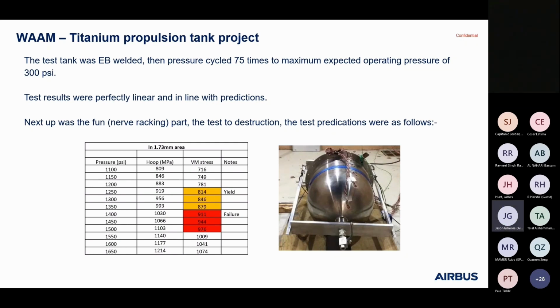So these are the test predictions. We predicted that it would yield between 1250 and 1350. And I mentioned the predictions earlier. I'd forgotten, I'd chucked this slide in earlier. You can see the strain gauges. So we constantly measured the microstrain throughout the testing. Nothing more to say than it was wonderful to be part of a successful test campaign where everything lined up with test predictions. The testing was actually done in a brand new pressure test facility at the Welding Institute in Cambridge. We're actually the first customer to use it. Okay, if we can move on.